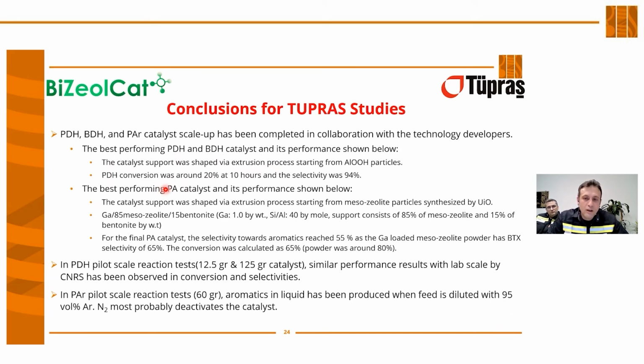We obtained almost thermodynamic conversion, around 20% at 10 hours, with selectivity around 94-95%. The best performing PA catalyst and its performance was around 1% gallium loaded mesozeolite.